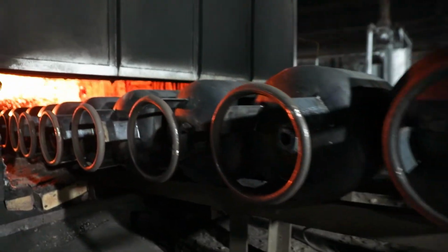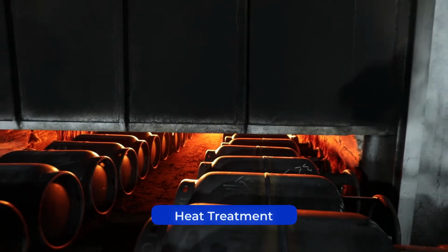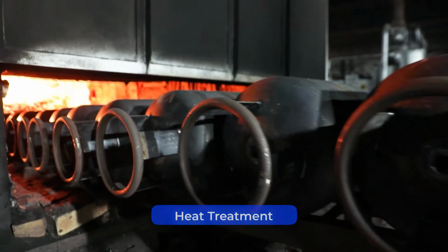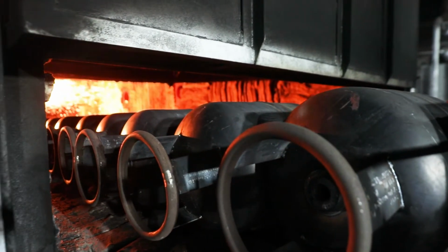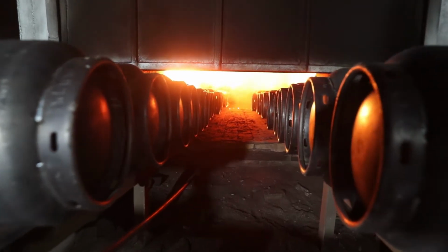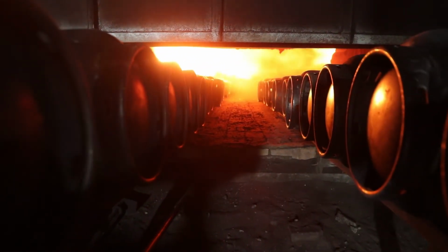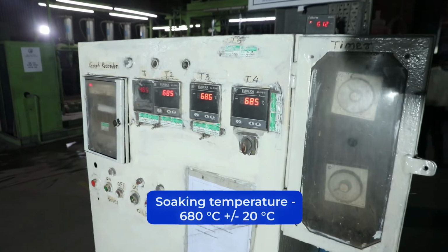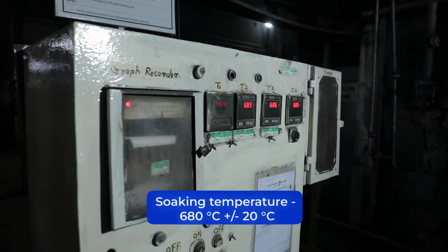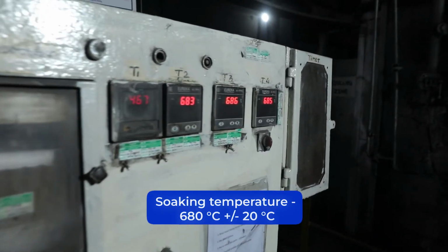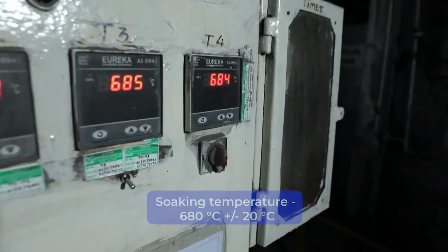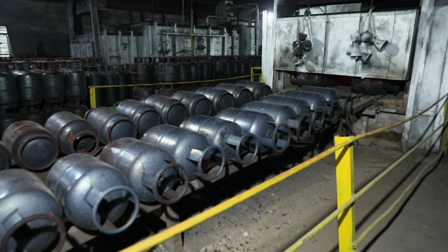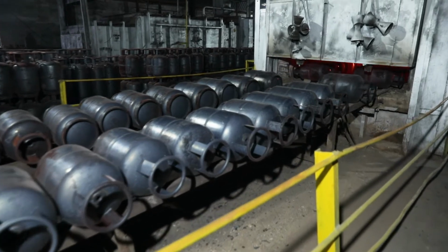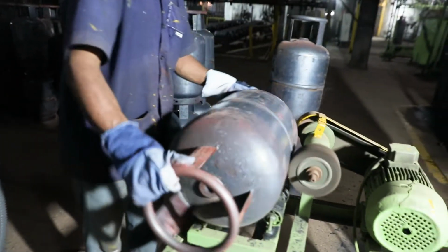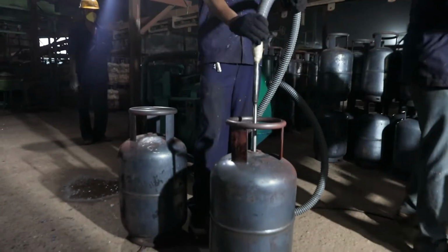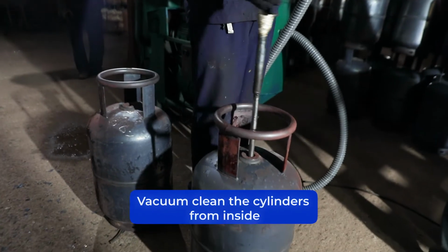All the cylinders are heat treated for relieving the stress. To load the cylinders, the furnace is oil and LPG fired continuous type with 2 rows to load cylinders. The parameters of heat treatment include a soaking temperature of 680 degrees Celsius plus or minus 20 degrees Celsius. Furnace process time is as per the capacity of cylinder to be furnaced with heat treatment. All the cylinders are cleaned from inside by vacuum to remove the scale.